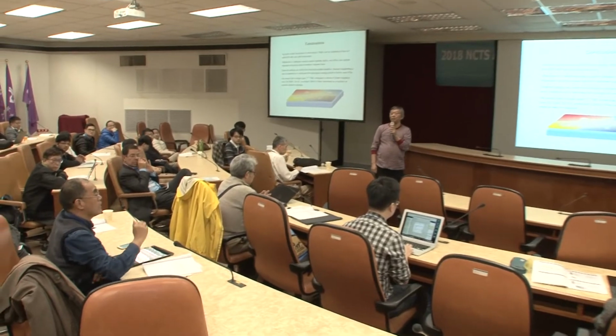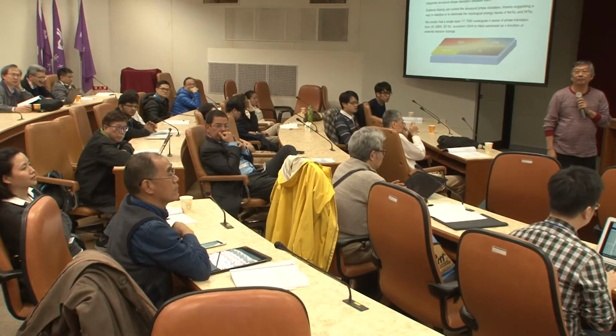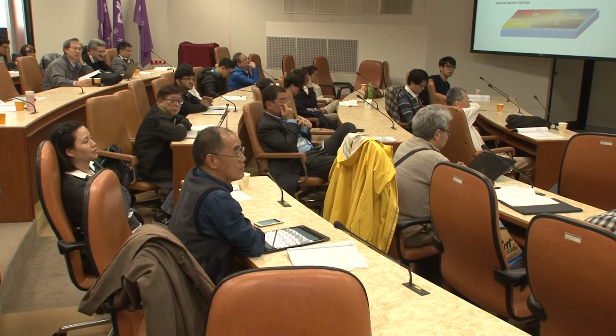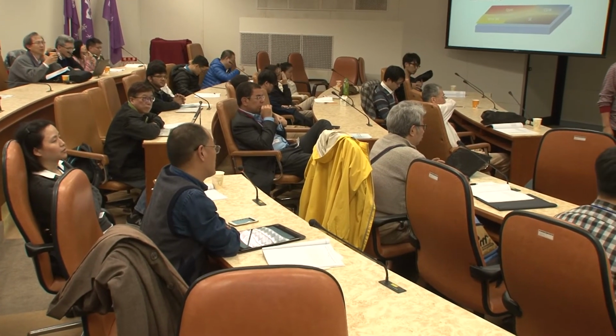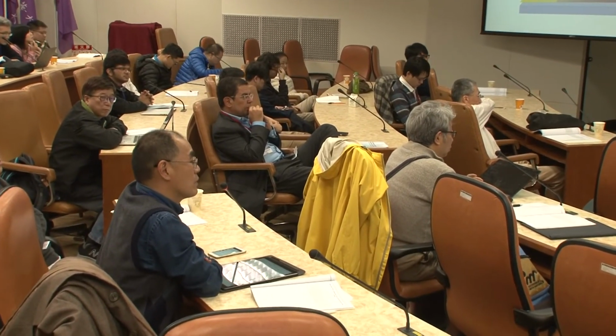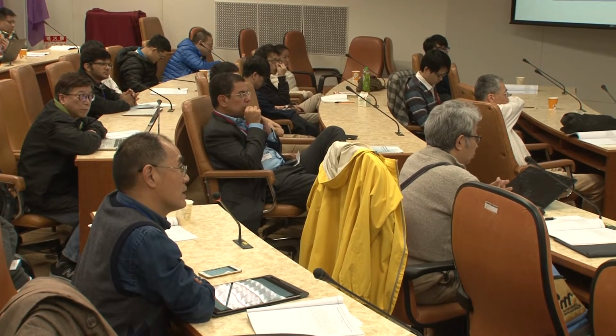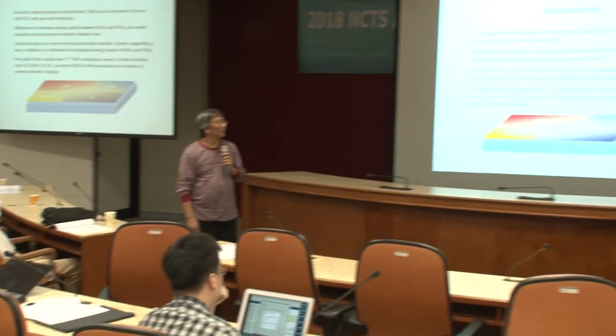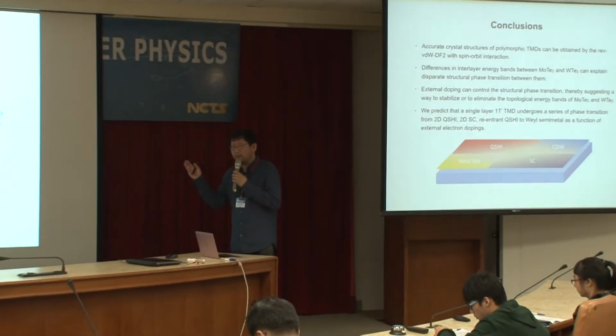On tungsten ditelluride, when you do the electron-phonon calculation, are you including the SOC? Did you include SOC? Yes. Right. So if you don't include SOC, how much will the electron-phonon interaction change? Very little, actually. It's marginal, less than 5%. So in principle, when you are dealing with two-dimensional materials, you can just skip SOC. But the important thing is that if you do have an inversion-breaking structure, such as orthorhombic, you need the spin-orbit coupling to reproduce the Weyl points. Without it, you cannot.